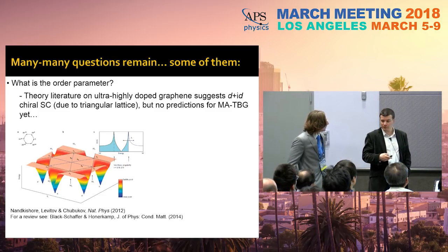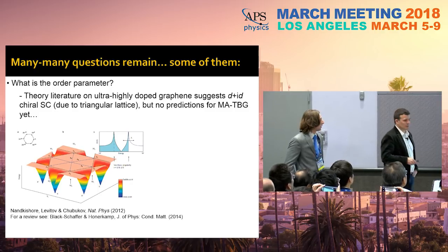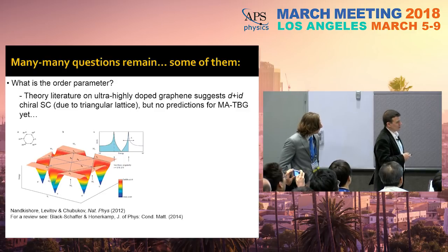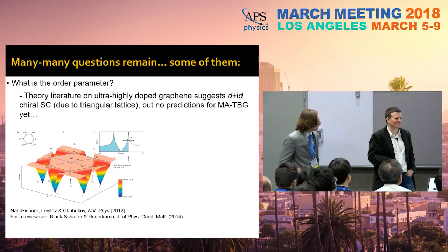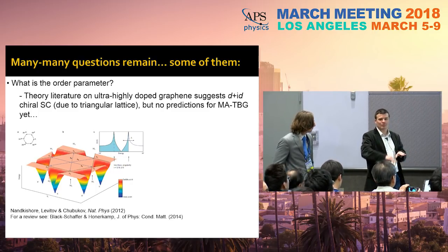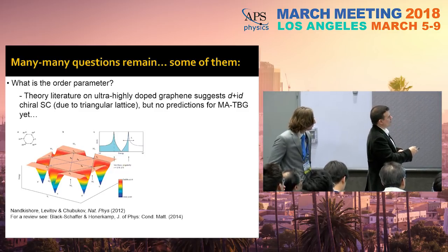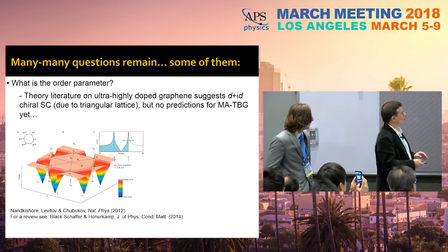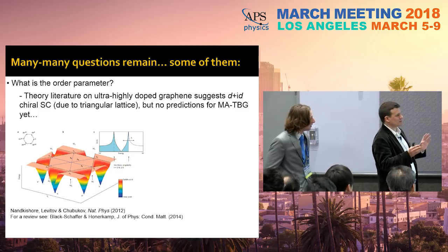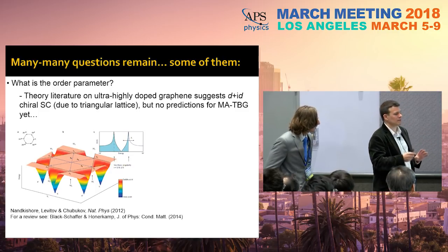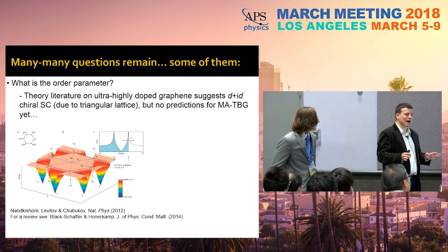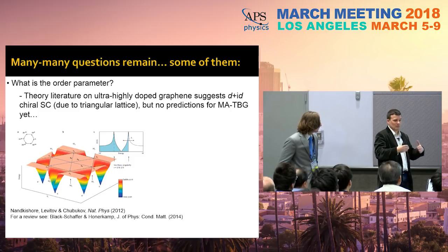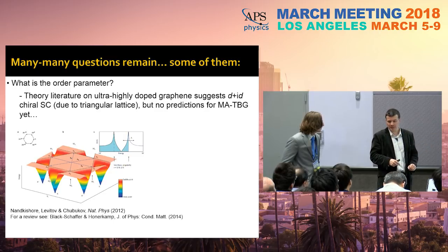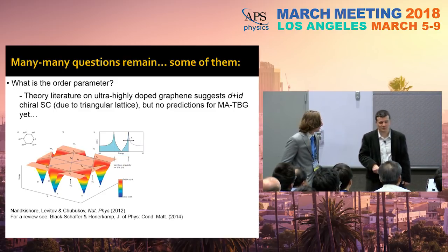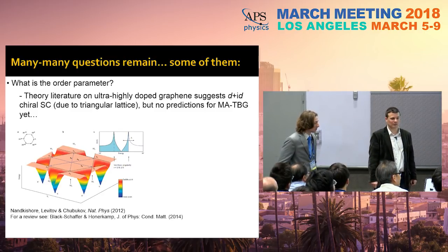There are no calculations for magic angle graphene superlattices, but there are hundreds of papers about what can happen for graphene, and also for bilayer graphene. I'm not including a citation here, but Oscar Vafek, I'm seeing him at the end, has also made predictions for bilayer graphene. It turns out that when you dope graphene with ultra high charge density, you reach this endpoint where you have a van Hove singularity, and people have predicted superconductivity. There are all kinds of other order parameters predicted, but it seems like most people coalesce around this d plus id chiral superconductivity, which is related to the triangular structure. So if somehow in the superlattice, which is also a triangular structure, that aspect is maintained, it could possibly be this d plus id. But I've also seen predictions for p plus ip, s plus minus, s plus other things. So it's very rich and has to be studied for these particular heterostructures.